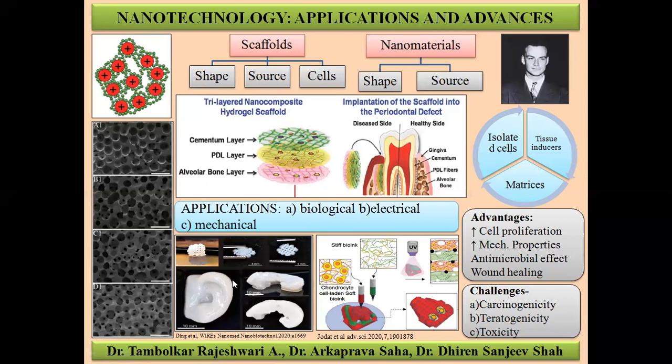In maxillofacial prosthodontics, auricular as well as nasal cartilages can be fabricated using various nanoparticles. This picture depicts 3D printed bionic ears which were implanted in mice in an animal study. The second picture shows the process of 3D printing of nasal cartilage. The soft bioink along with the stiff bioink from both the syringes or cartridges are loaded in the 3D bioprinter, and then dual printing is carried out on a specific sensor to form the nasal cartilage over it.